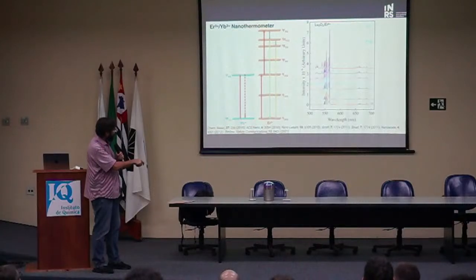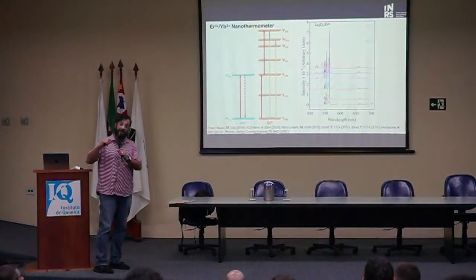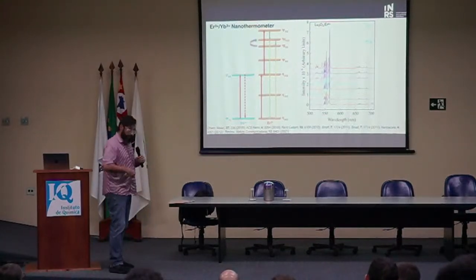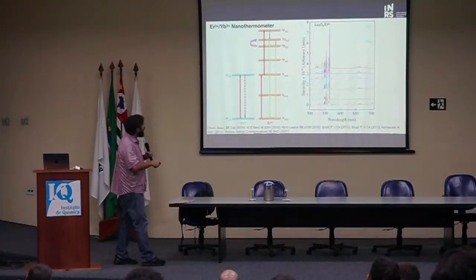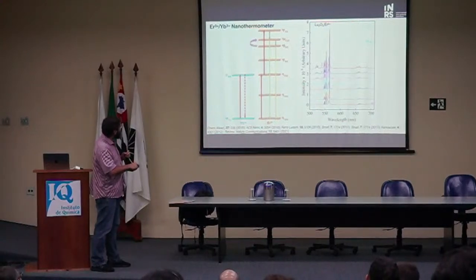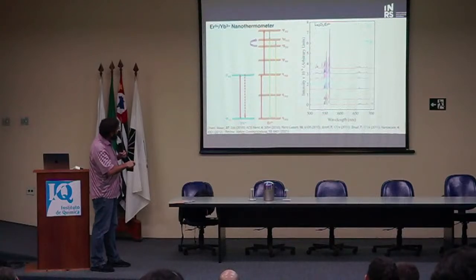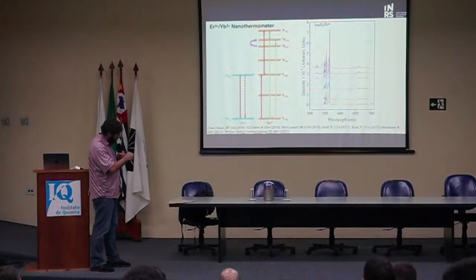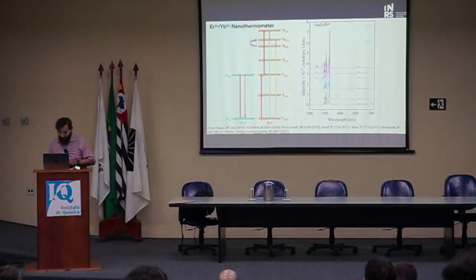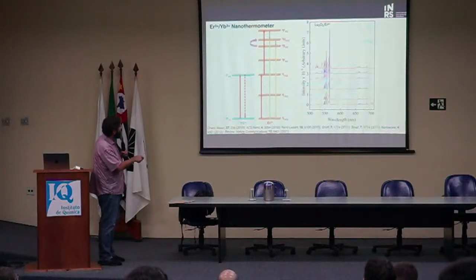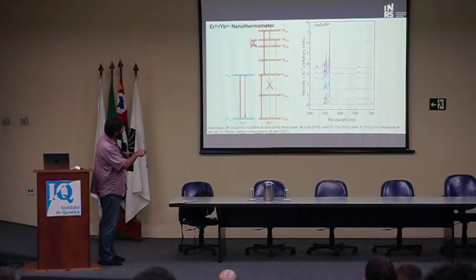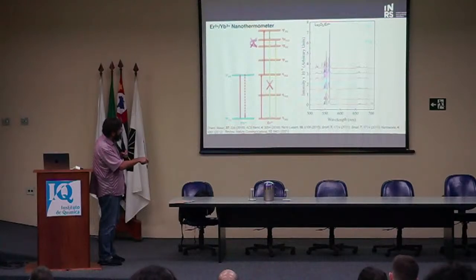So it's this big guy here. But because these two states are so close in energy, they're in thermal equilibrium, so they obey the Boltzmann law. The lower state can repopulate the upper state, and then you get this emission here. This repopulation is Boltzmann, so it's controlled by temperature. When you decrease the temperature, as you see here, the probability of thermalization happening decreases until you pretty much kill this emission. And so now you have this peak here, and obviously these ratios change.